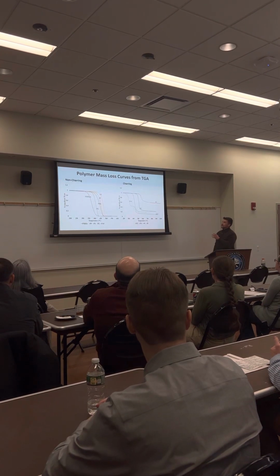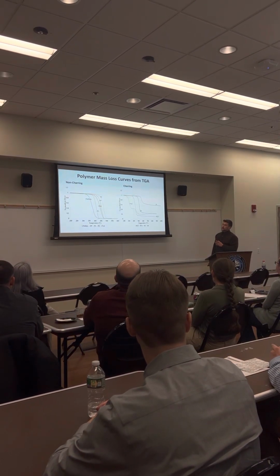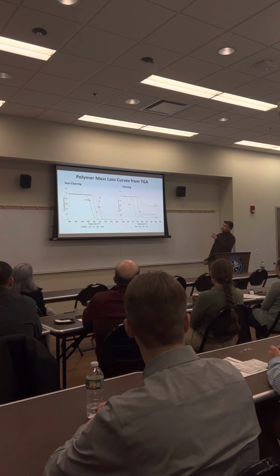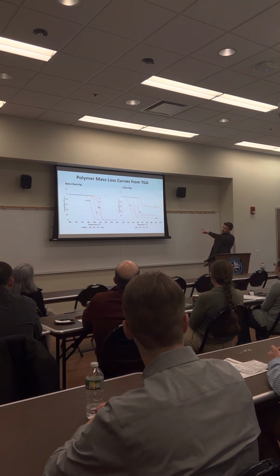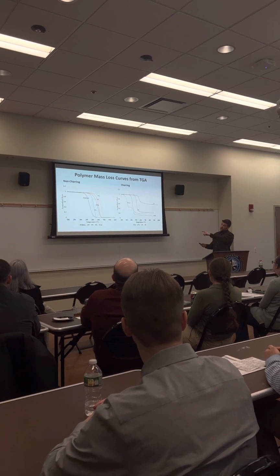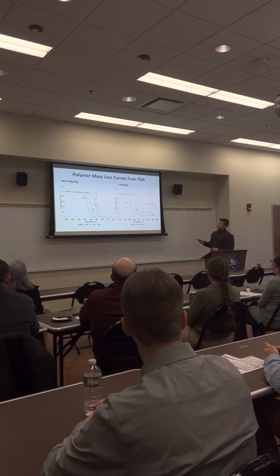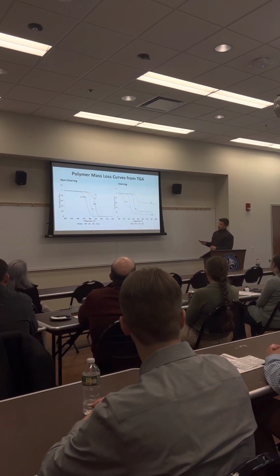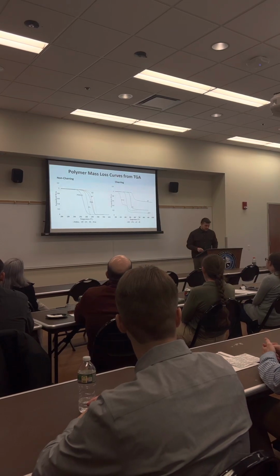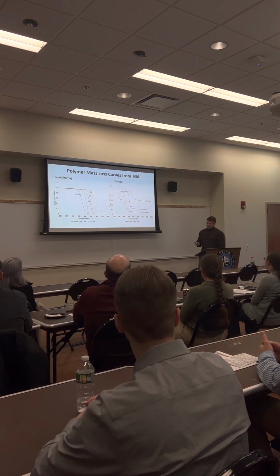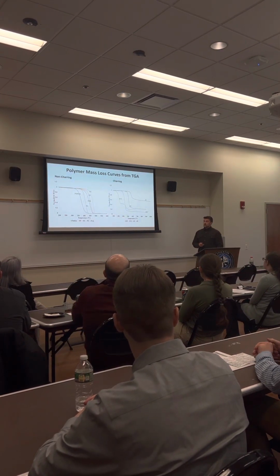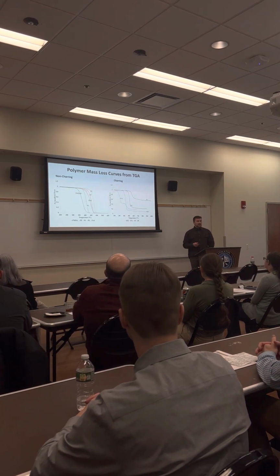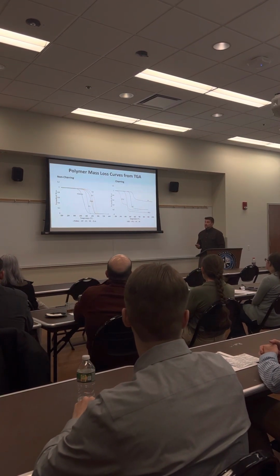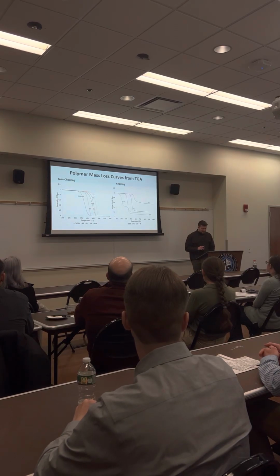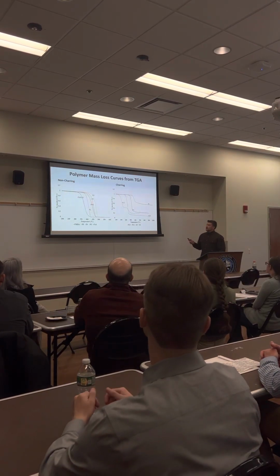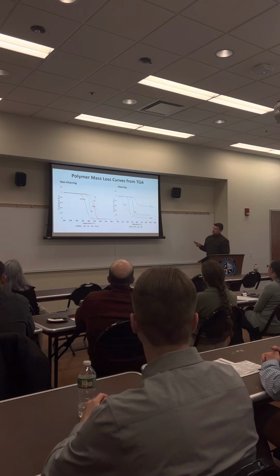These are mass loss curves that we plotted for specifically PMMA, which is polymethyl methacrylate, alongside all the other non-charring plastics, and then PVC with the other charring plastics or polymers. They're all plotted at a rate of 10 degrees Celsius per minute for the sake of comparison. We'll get into the other rates soon. You can see their behaviors are much different than these.